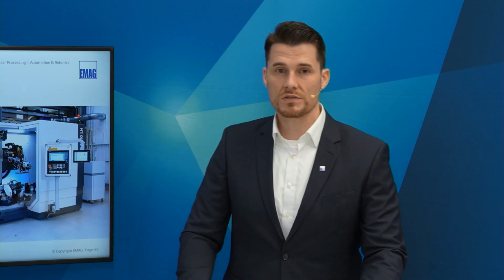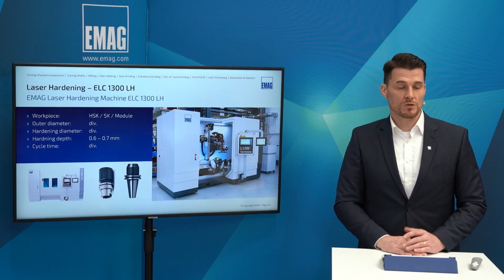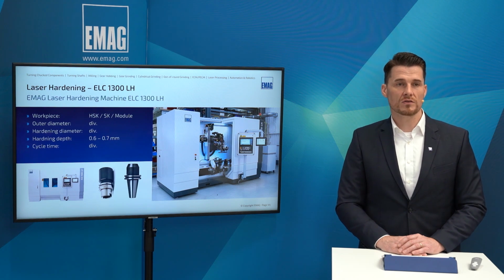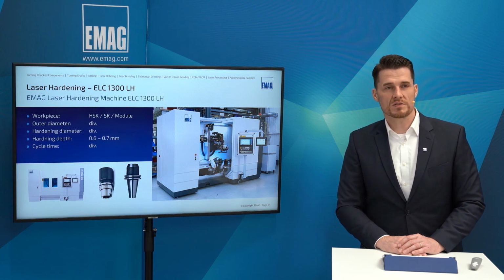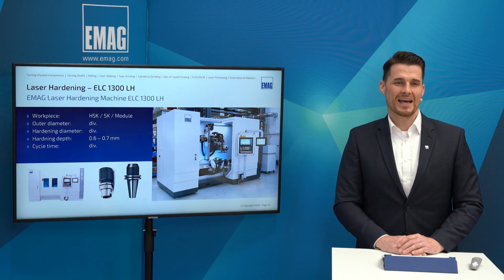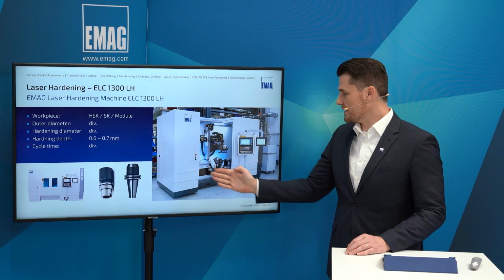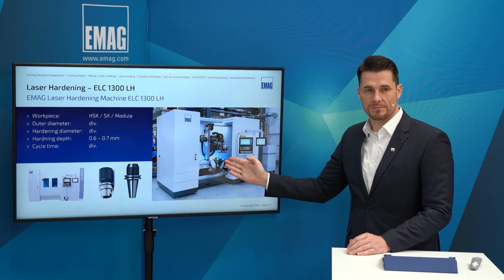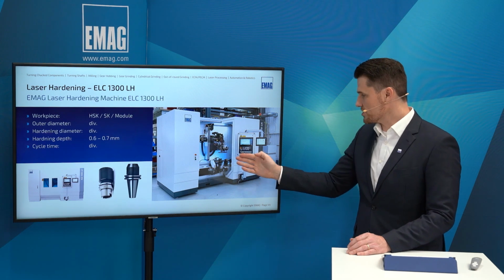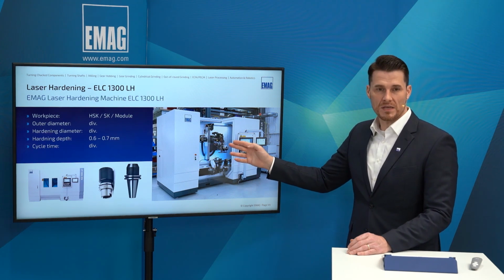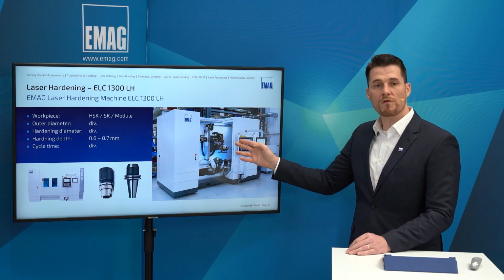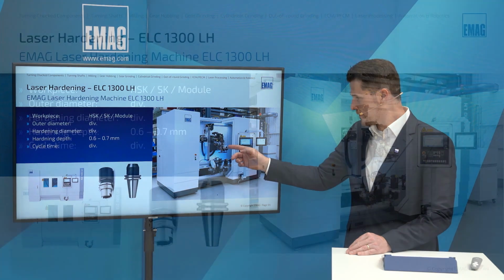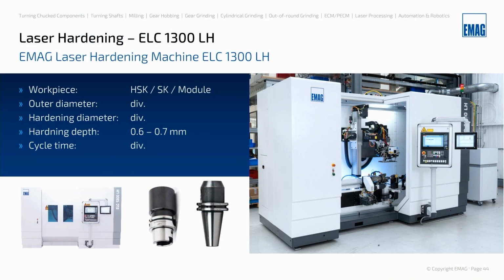The machine which we are using for this is the ELC 1300 LH machine, which is shown here. It was used for this example for those HSK tool holders. Hardening depth was between 0.6 and 0.7 millimeters. And you can see on the machine also here a huge front door, very well accessible. The operator is standing inside the machine literally. We see here again the PFO, the programmable focusing optics, which is the weld head, let's say, and it is mounted even on 4 NC axes to give it a perfect flexibility.